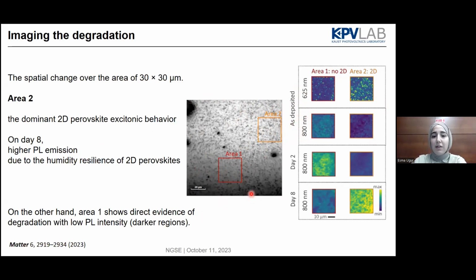But after some time, when we keep these samples in an ambient environment, after like 8 days, again, the average PL on this area for the one with 2D is actually higher than the one without 2D, which is, I think, the direct evidence of the degradation of the perovskite when you keep them in air after some time.